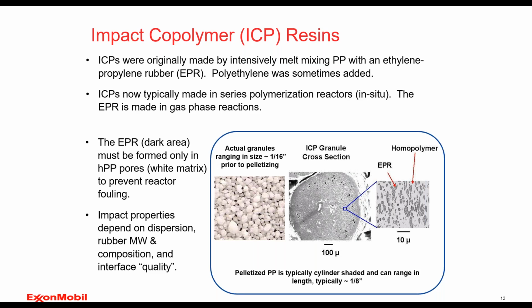They might look like granulized sugar or coarse sugar or perhaps powdered laundry detergent, that type of granule. And when they're specially designed for the incorporation of ethylene to make an ICP, those granules are porous in nature. And so when the homopolymer is made, typically in loop reactors, and then gets fed on to the reactor that's in series, being that gas phase reactor, the ethylene is incorporated and infused into the porosity of that granule, and that finally makes the final result, the ICP matrix or morphology shown on the right side of that picture.